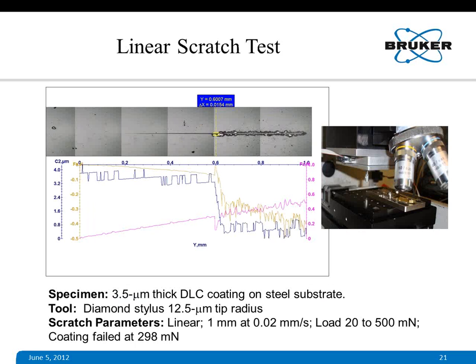Now I will present some of the advanced scratch test results, which are obtained using the CETR scratch tester. This scratch test was done on a DLC coating on a steel substrate using a diamond stylus with 12.5 micron tip radius. This red line shows the normal force, which is progressively increasing, and Fx, which is actually showing a sudden change at the point of failure. And on the optical image, you can see that the coating has completely failed here. It scratched through the coating.